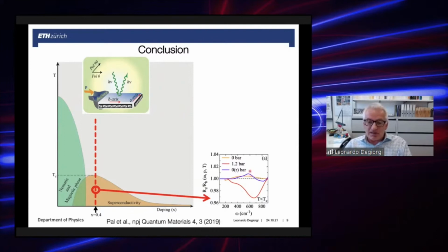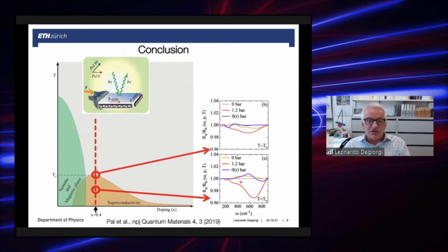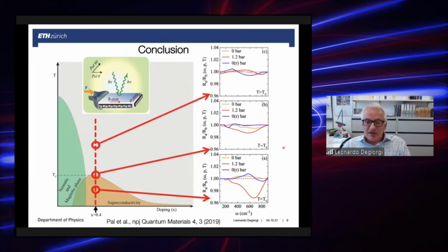That anisotropy turns out to be fully reversible upon tuning the external symmetry breaking field, which is in our case a uniaxial stress. This behavior is just incipient at TC, but we were not able to observe any stress-induced anisotropy in the normal phase. The main implication of these results, as I just showed you in the previous view graph, is that there's apparently an anisotropy in the superconducting gap, which is the relevant energy scale of the superconducting state. And this may be considered as a smoking gun evidence for the realization here of a nematic superconductor.